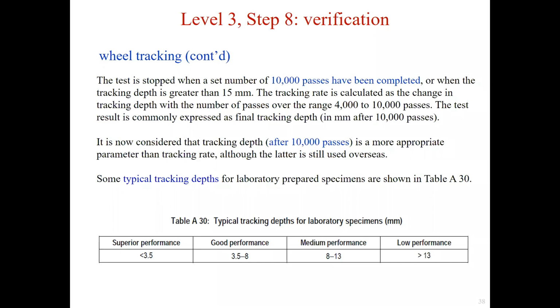For the parameter of wheel tracking rate, it is calculated as the change in tracking depth with the number of passes over the range of 4,000 to 10,000 passes. The result could be converted and expressed as the final tracking depth after 10,000 passes.